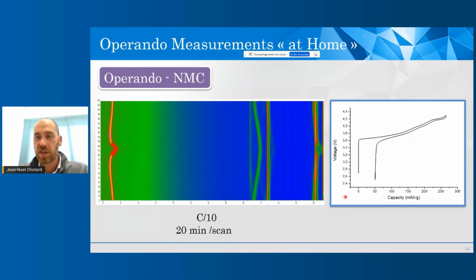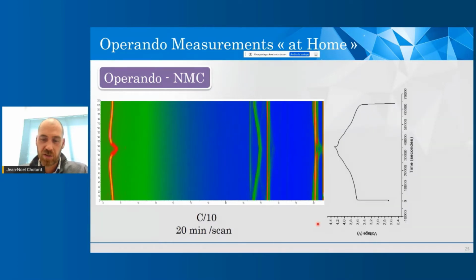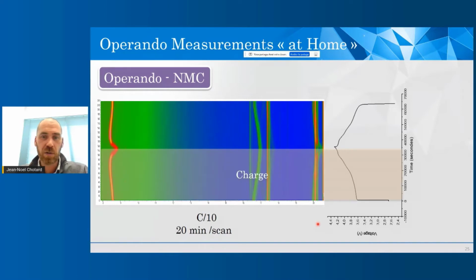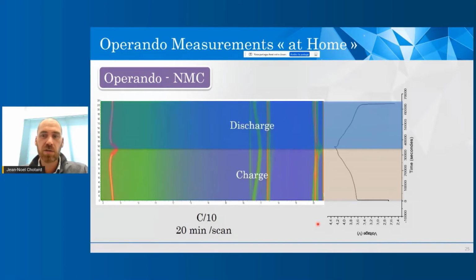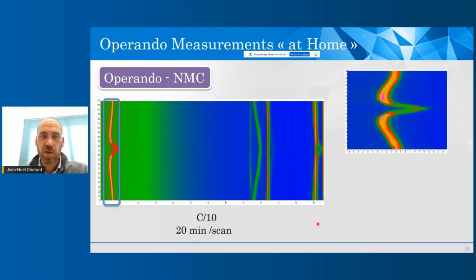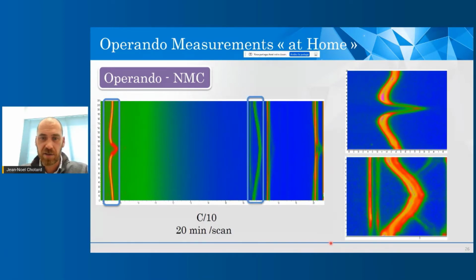This is here the corresponding electrochemical curve, and usually we try to plot it this way so we can see what's going on during the charge and what's going on during the discharge. And if we look closer, we can clearly see the different changes of the peak position during the cycling of the battery. That's at low angle here, that's the 003 reflection, and that's some more complex behaviors that you can see.